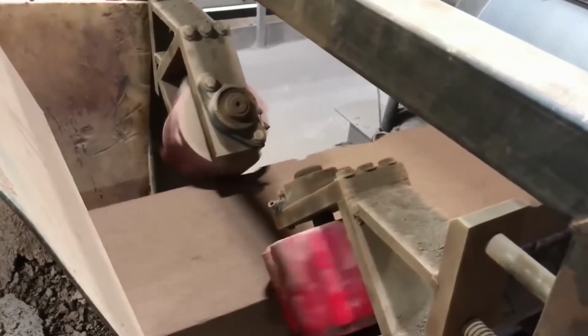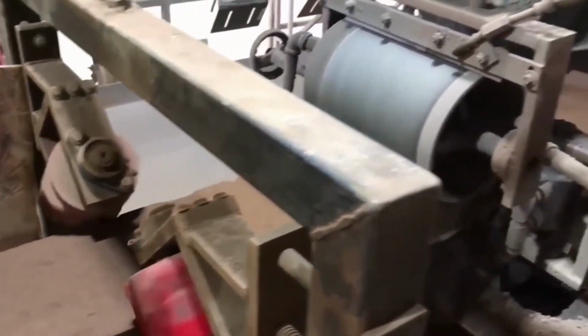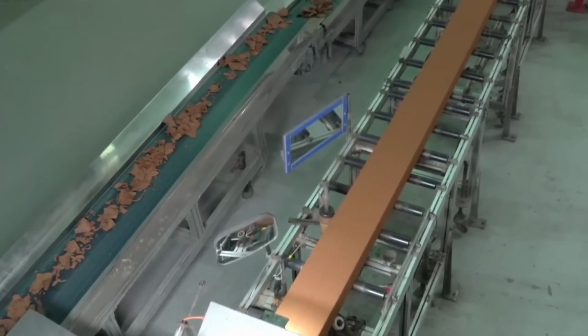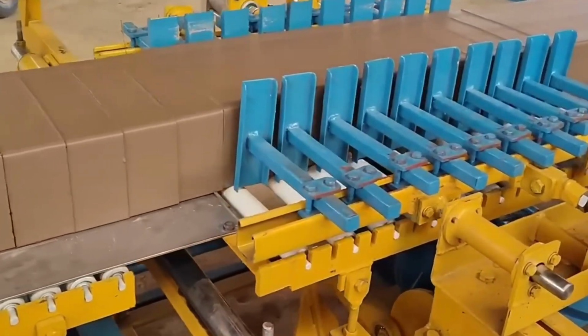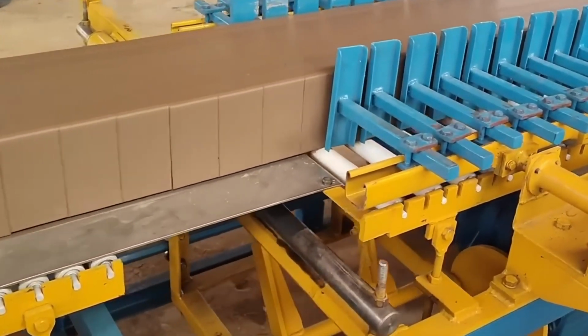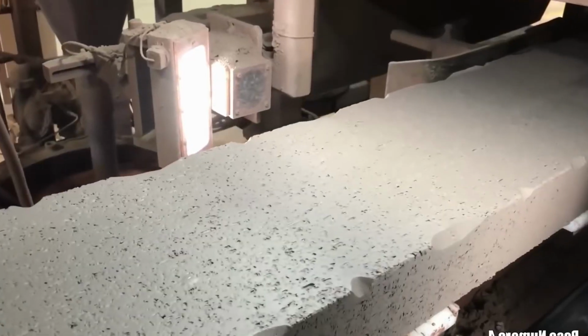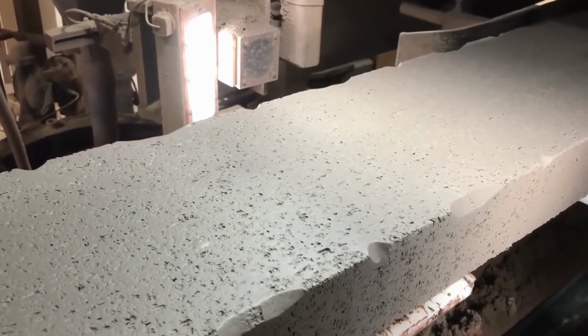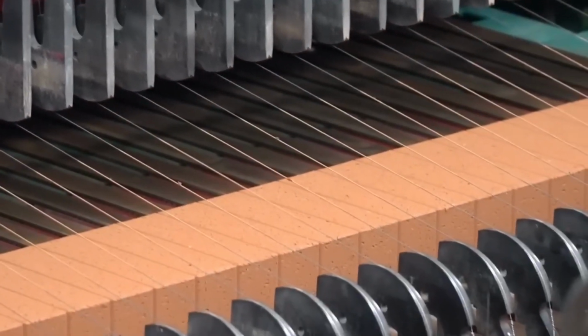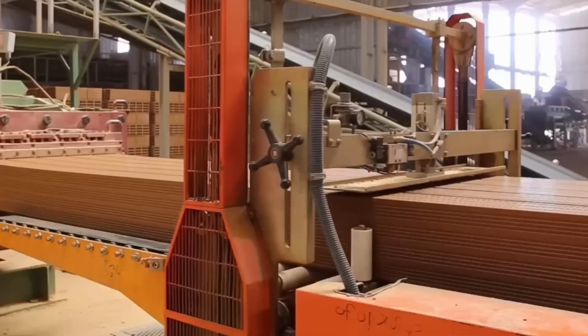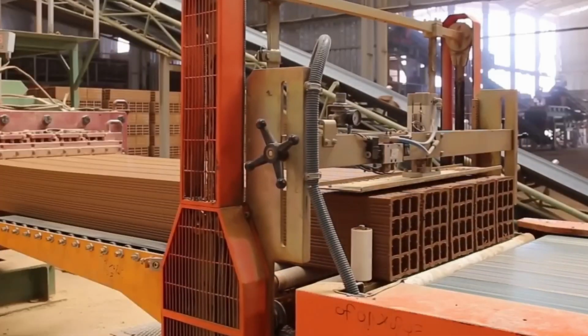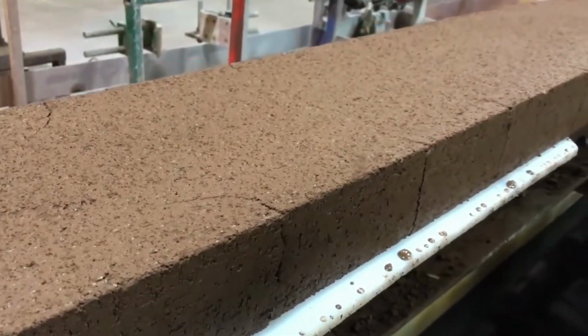trays, or shelves. Drying is one of the most delicate phases of the entire process. The damp clay must lose water gradually and in a controlled manner. If the surface dries too quickly while the interior remains moist, a shrinkage differential occurs. The outer layer hardens, the center continues to shrink, and cracks appear. This is why factories use industrial dryers, long tunnels, or enclosed chambers where temperature, humidity, and air circulation are controlled.